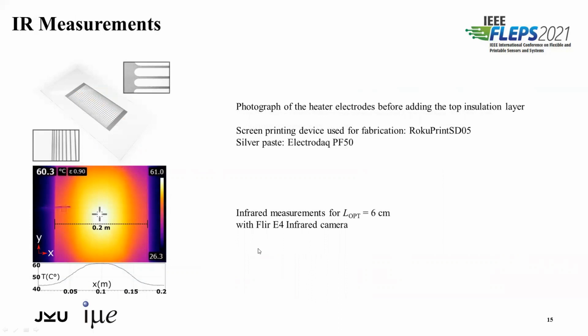The final slide shows a fabricated sample of the heater before adding the top insulation layer, so that you can see the screen printed electrodes on top of the insulated steel substrate. In these close-ups, you can maybe roughly see the resolution of the used screen printing mesh. The conductive heat electrode lines are realized by screen printing conductive silver paste on top of sheet metal substrates with the pre-coated insulation and cured at 140 degrees Celsius for 240 seconds.